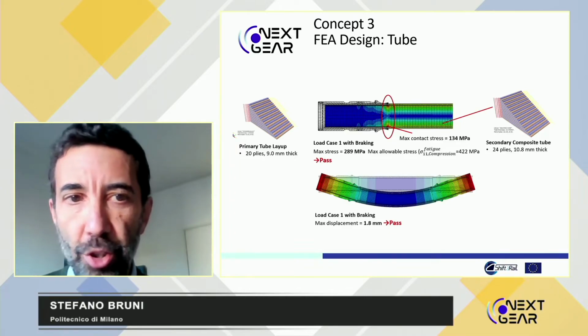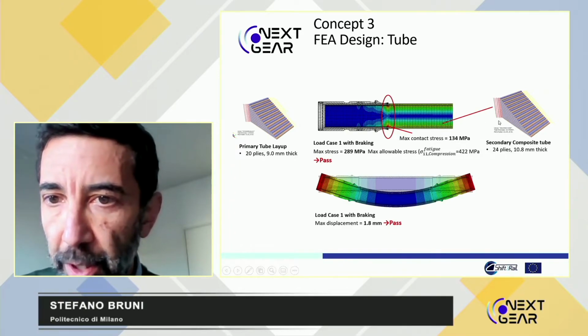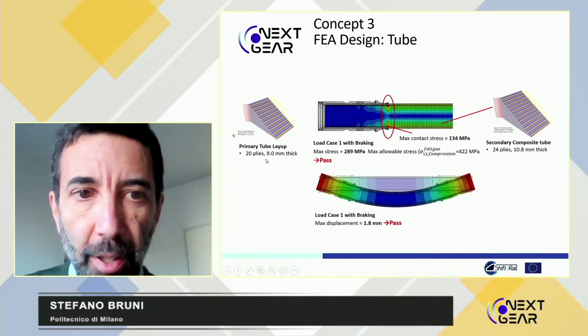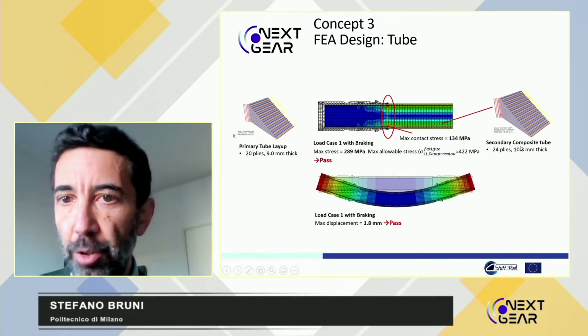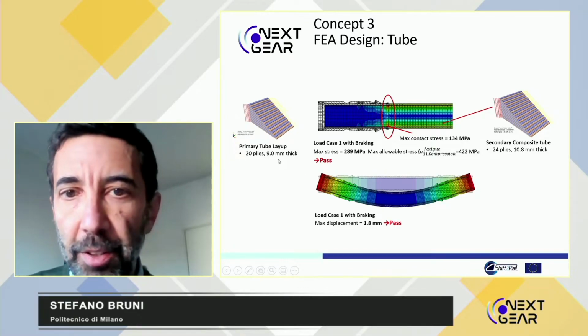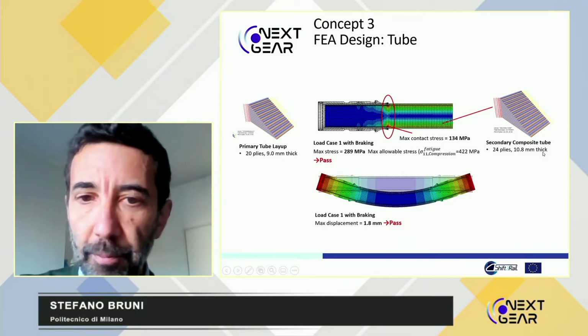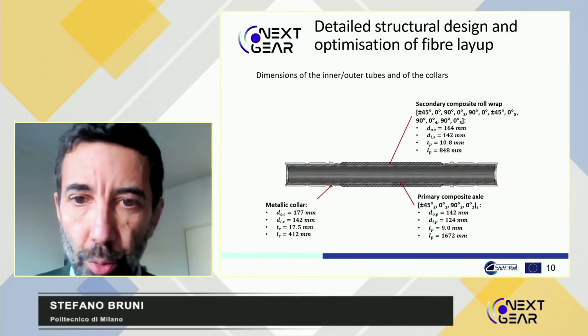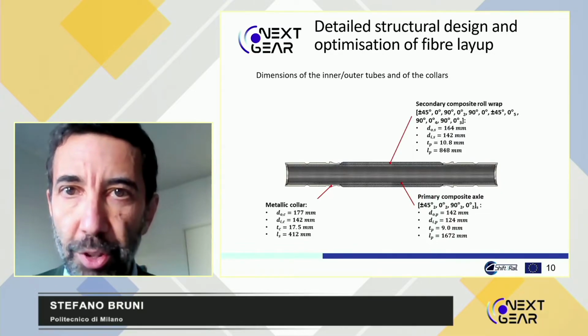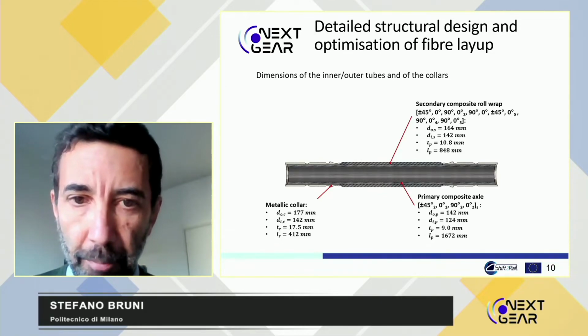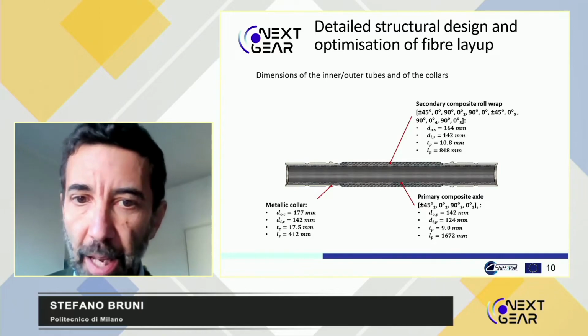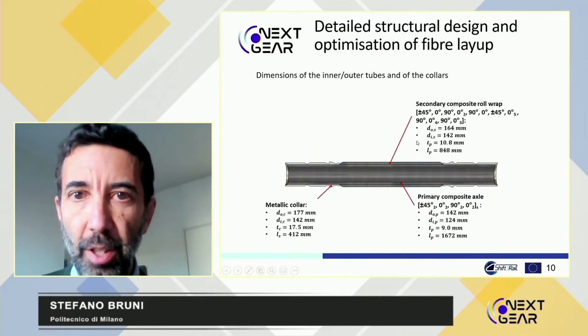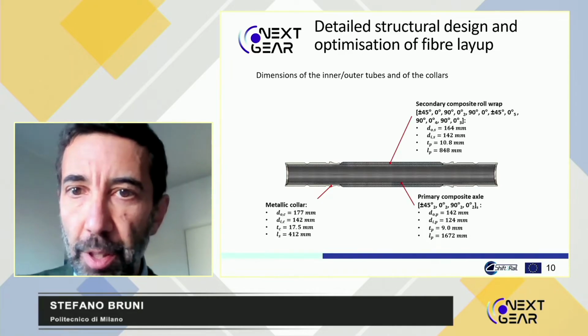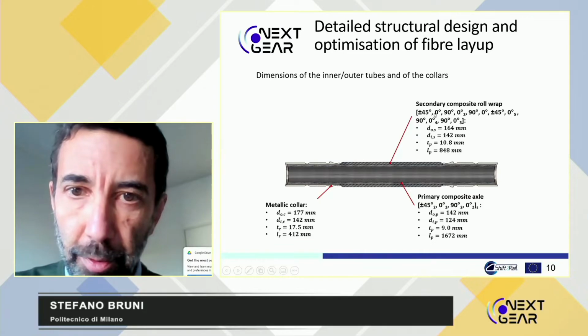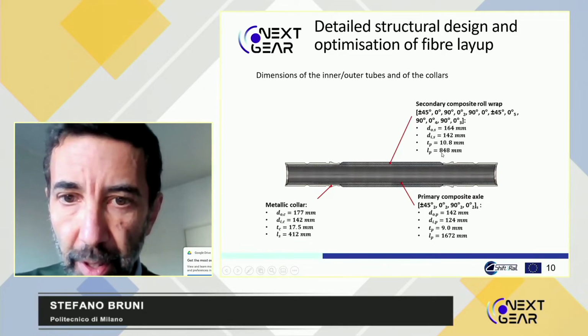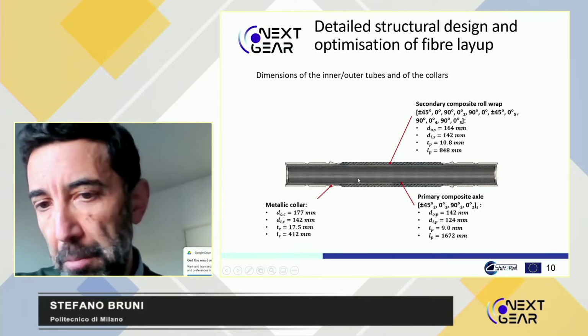Nevertheless, we could solve this issue by adding a secondary composite tube and by optimizing the layup of the primary inner tube and secondary outer tube in terms of the number of plies, thickness of the plies, and so on. And this led us to a final, frozen design for the complete hybrid metal composite axle, which is summarized in this image, where you see basically the directions of the fibers, the thickness of the different components, and the main geometric properties.